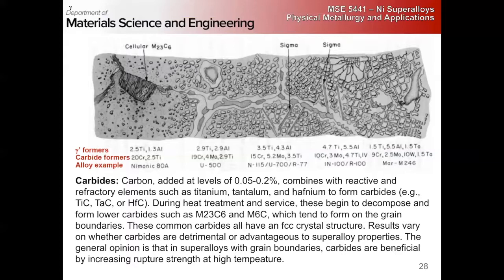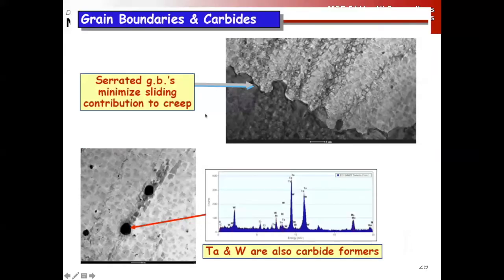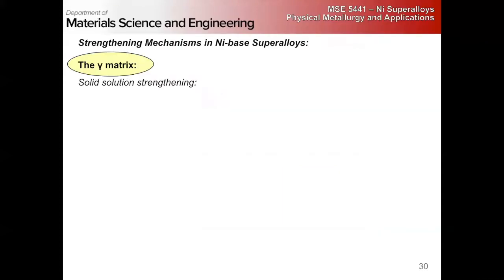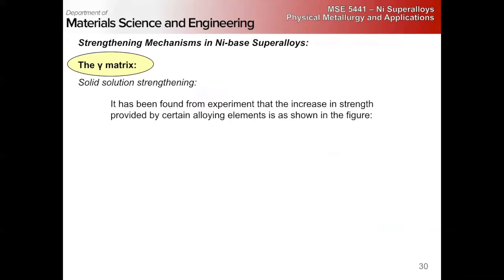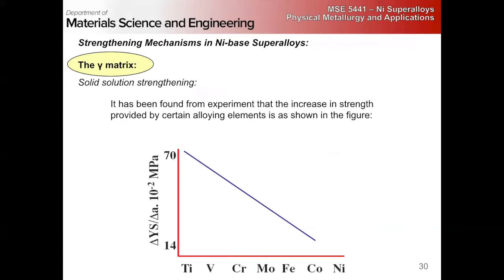right? So they can be fairly coherent. They are beneficial at high temperatures because they lead to the formation of these serrated grain boundaries, right? Which are very favorable for creep, right? Because at high temperatures, grain boundary sliding and grain rotation are critically important creep rate controlling mechanisms, right? So if you have a tortuous grain boundary like this, you do not have nearly the ease of grain boundary sliding.